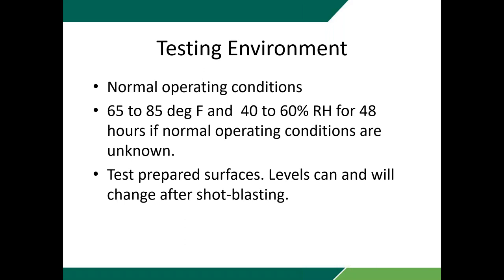And the reason is because the levels of vapor drive will change when we actually do something like shot blast the floor. Again, you remove that top layer and you've got to let that slab acclimate. You've got to let the moisture equilibrate itself throughout the slab. So when you pull the surface off the slab, you've got to let it equilibrate.